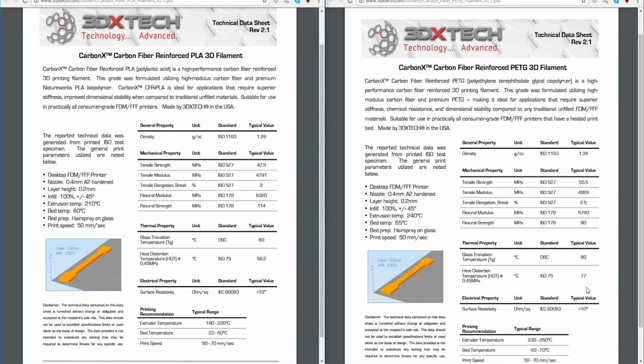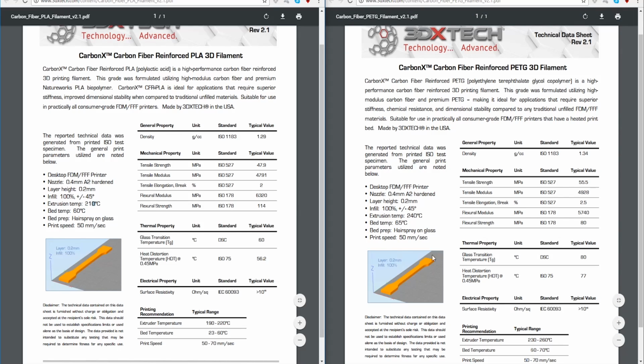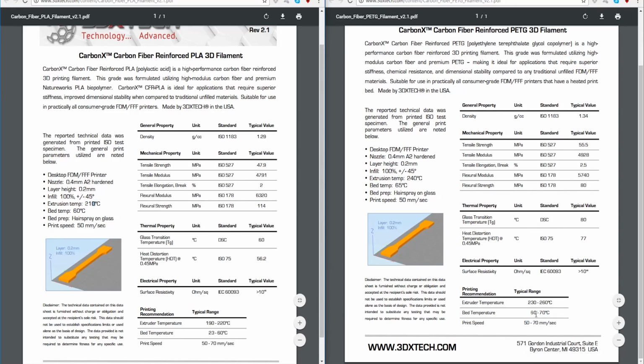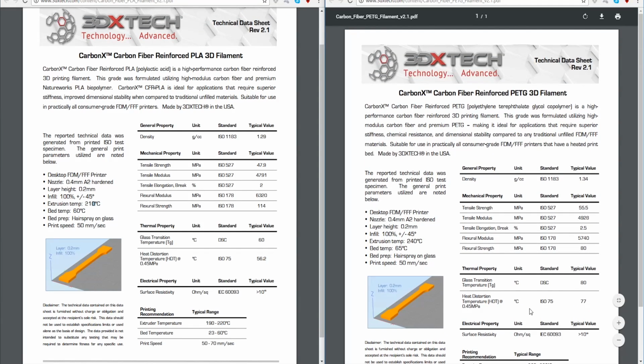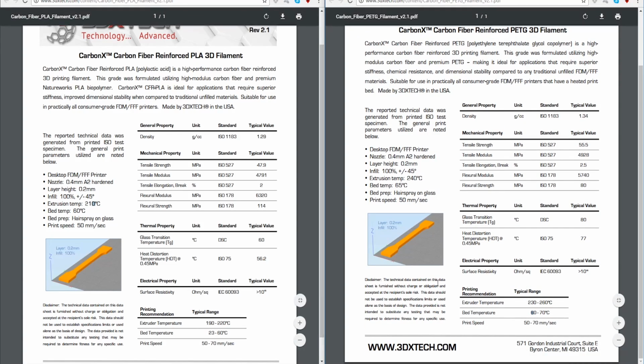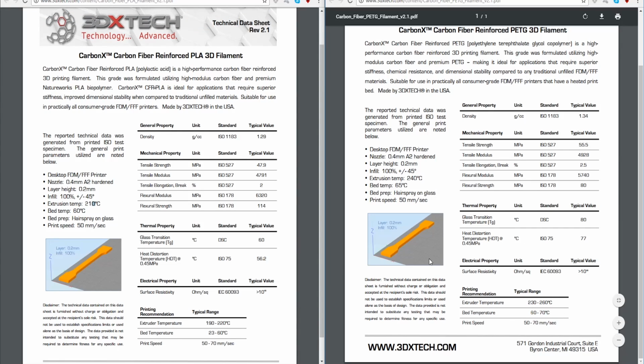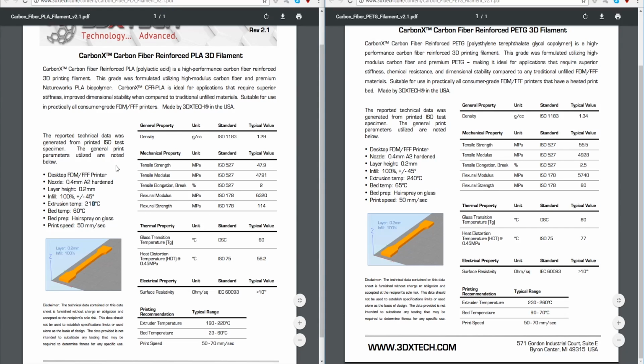Okay, so versus PLA, this is probably one of your better all-around bets. It's one of the better ones to pick. However, you need a heated bed. Here it's saying the test was at 65C, but this one was also 60C. So these are almost one and the same here. And so, yes and no. It could have some better properties in some states, and might beat out PLA. So here, kind of neck and neck, but also again better stability. But you need a different type of setup on your printer for higher temperature prints. So this probably won't work as well in your printer as this one. So you'd probably pick the PLA.